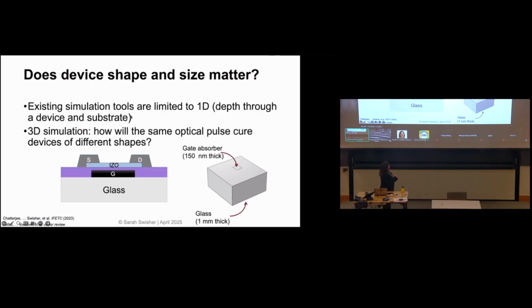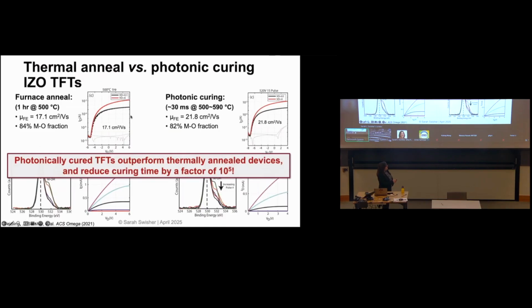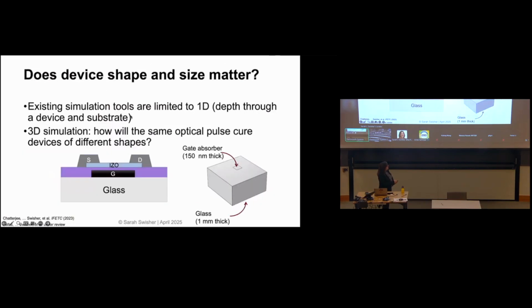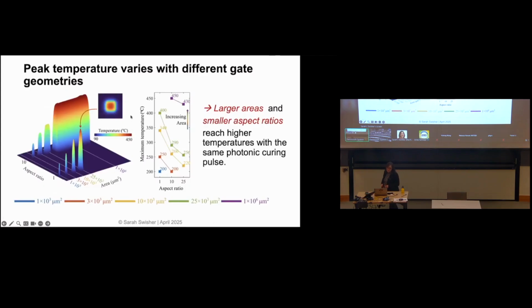And so we took our TFT structure here, and we modeled it in COMSOL. So this is the glass substrate. Here is that gate absorber. And we developed this 3D model using the heat transport equations to figure out how the heat is transported in 3 dimensions when we deposit this optical energy on the top. And it turns out that there is a huge difference in the peak temperature that you reach when you have a different size or a different shaped gate.